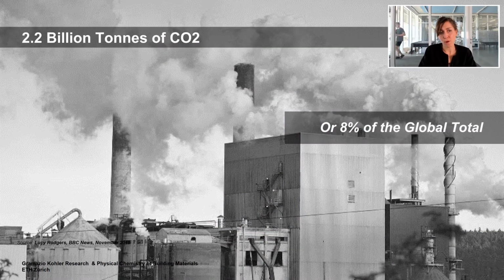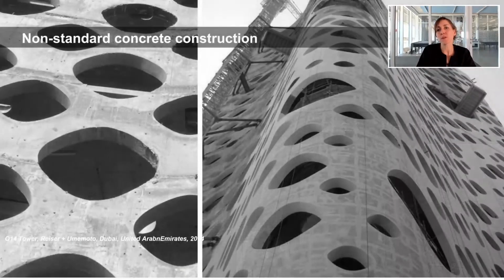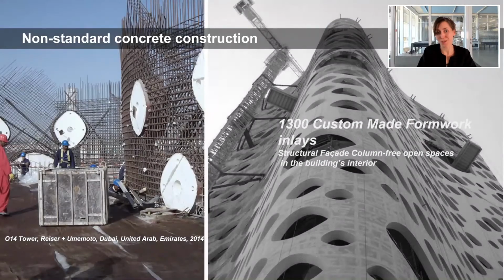Now, knowing that concrete causes 2.2 billion tons of CO2 to be emitted into our global atmosphere, we might need to rethink the way we construct, which is already being done thanks to digital fabrication and seeing buildings such as the O14 Tower by Reiser and Umemoto, which was erected in 2014 with the goal of saving material for the overall structure. All the void zones that you see are to remove material where it's actually not needed. However, to do such structures requires custom formwork inlays, which in this case was 1,300, which were used one single time.